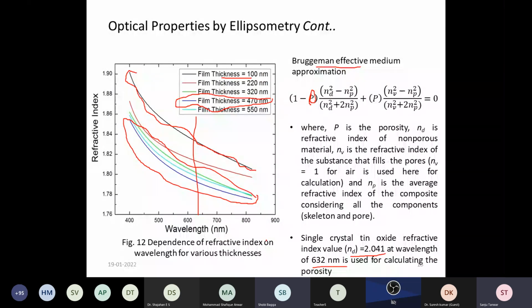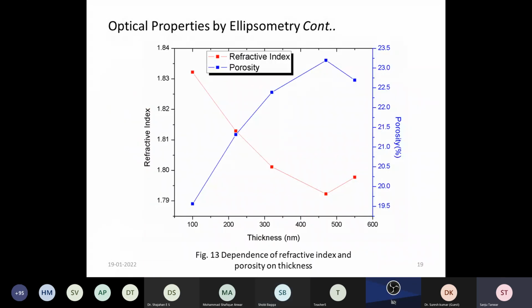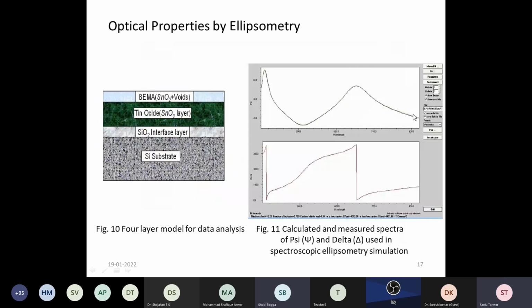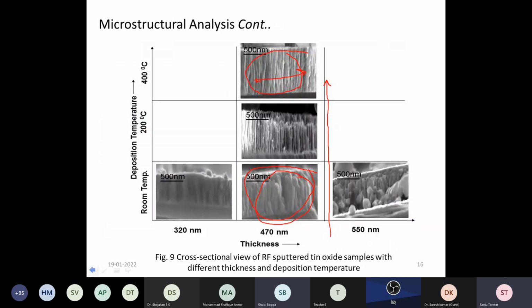We have compared the films at 632 nanometer because most ellipsometry uses light at 632 nanometers. And then we have correlated what we have obtained. We have obtained that the refractive index is decreasing as our thickness is increasing, and we are getting the minimum refractive index for the 470 nanometer film. So this indicates it should have the highest porosity, since it has the lowest refractive index. And this can also be visualized using the cross-sectional SEM over here.